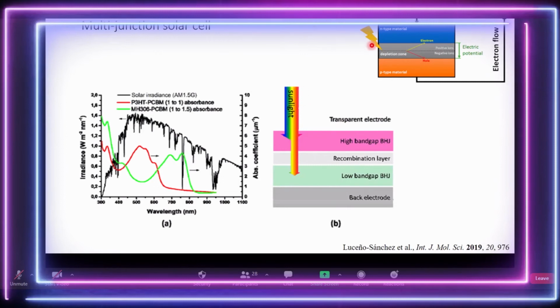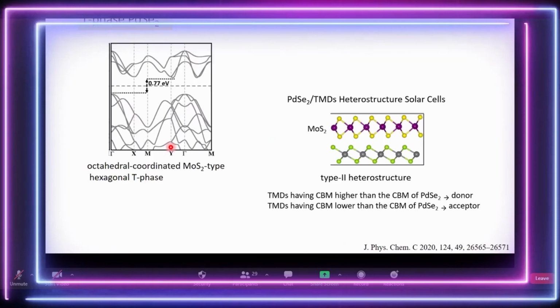For this case, when the photon comes in, it simply takes care of the material's band gap, whatever it may be. But here, because of the high band gap and low band gap, what we are capturing, you can see in the radiation, the peak is about 500 nanometers, but also, because of the low band gap, we are capturing a large part of the so-called red region. So the absorbance of the solar radiation becomes a little higher than what you expect in a single material. And then again, it depends on the location of the conduction band of our MoS2 or PdSe2. One can see it can act as a donor or acceptor for the material.